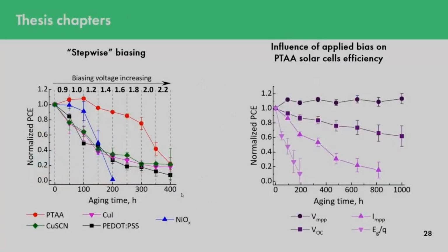So first of all, we decided to try an accelerated experiment, which is called stepwise biasing, when we applied different biases to our devices and stepwise increased it up to 2.2 volts. And you can see that all devices start to degrade at different applied voltages, which also confirms our previous observation that we have some kind of threshold voltage in the devices. And thus the question arose that we should choose the proper biasing voltage for all further experiments.